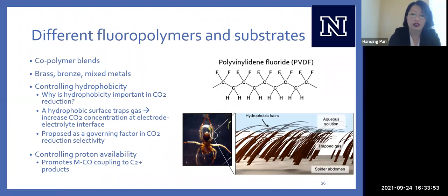If we apply this to CO2 reduction reaction, if we have a very hydrophobic electrode surface, that can also help us trap CO2 gas. And if we can increase the local concentration of CO2 at the electrode surface, we can then perhaps control selectivity. And so hydrophobicity has been proposed as a governing factor in CO2 reduction selectivity.